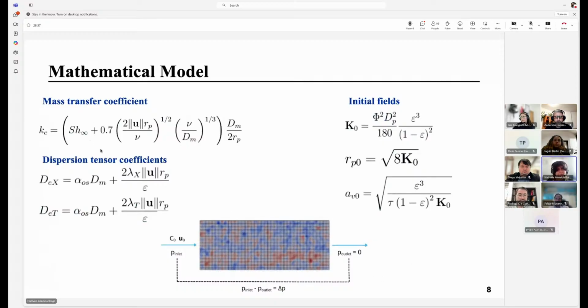We have the components for mass transfer and the dispersion tensor. And the other fields, permeability, pore radius, and interfacial area, need to be initialized too, and they're initialized with correlations with the porosity I get from the image.